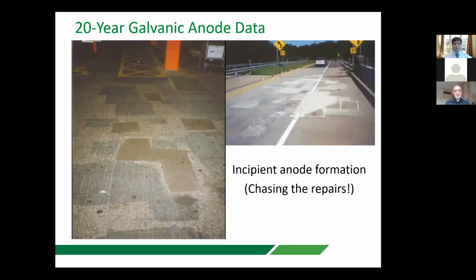Now, why am I talking about corrosion prevention? Well, one of the initial problems that people who are repairing concrete construction were finding was that when they carried out a repair, a patch repair, i.e. remove any cracked concrete, remove contaminated concrete around the steel, that will make a very good repair, and it looked wonderful. But corrosion would initiate at the periphery of the patch repair very quickly. 2 to 5 years later, they would have to come back and repair the adjacent area.